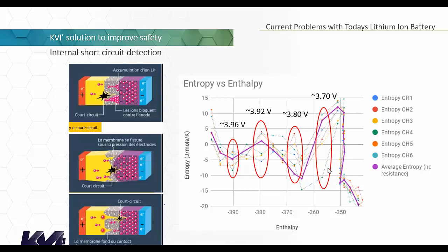Solid line. Now, if we create a short circuit in the battery, you can see, for instance, at 3.7 volt here, the entropy value at a very specific enthalpy value or voltage, which is here 3.7 volt. At 3.7 volt, you can see that the entropy value is different in the batteries that have an internal short circuit as compared to the battery that has no internal short circuit. So this is a very, very simple and very straightforward technique. If you have a battery and you know the chemistry, you can very easily determine at which voltage you can see the difference between a battery that has an internal short circuit and not. So in this case, 3.7 volts.